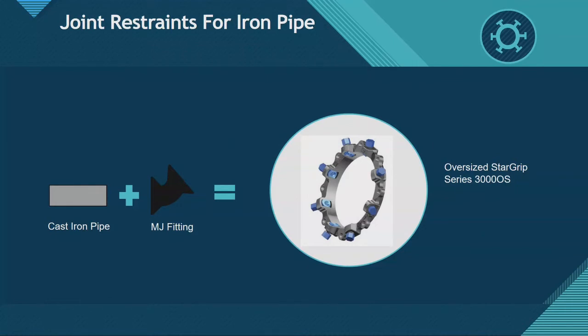Cast iron pipe, pit cast. If you're going to install an old pit cast pipe, you can't use a standard ductile iron pipe restraint. The reason is pit cast pipe has a larger OD, so you need to compensate for that larger OD. How you do that is most manufacturers will have an oversized restraint that will slide over your pit cast and go on.